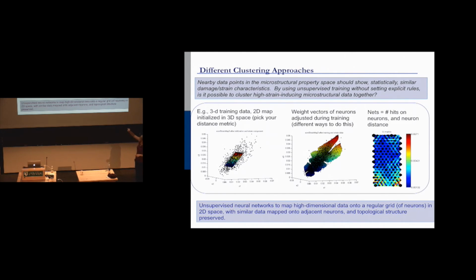And then the tenet that we use is that if you have points that are clustered in the microstructural variable space, they should match the clustering on average in the damage space. So we basically try to make these two maps match. And we do that by something called self-organized mapping. Self-organized mapping is a machine learning algorithm that basically takes multidimensional space and brings it down to 2D.